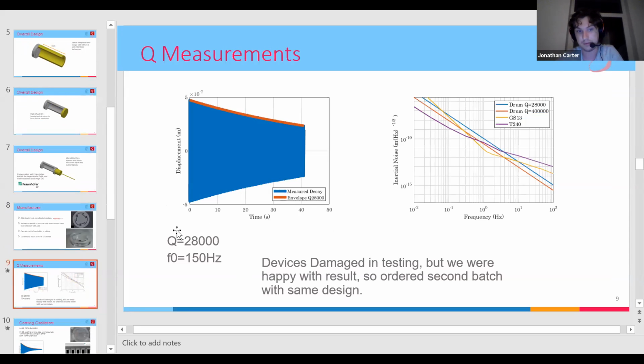We had quite a variety of quality factors. The best we achieved was a quality factor of 28,000 with quite a thick design, and a natural frequency of 150 hertz. The other devices had quality factors typically ranging from about 7,000 to about 20,000 in our first batch. So we ordered a second batch of oscillators of the design that performed the best.